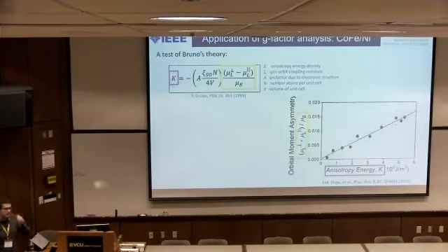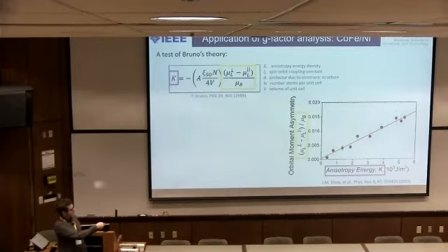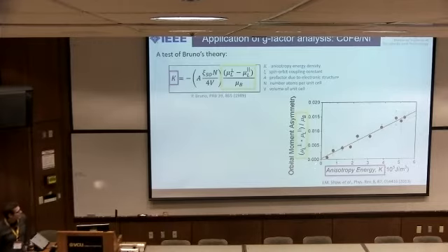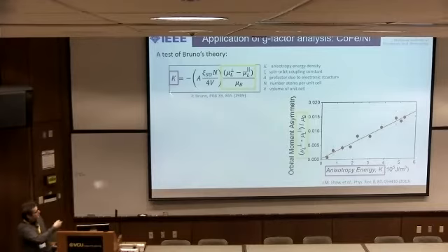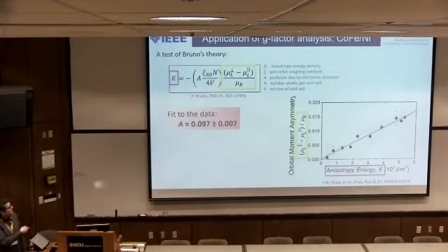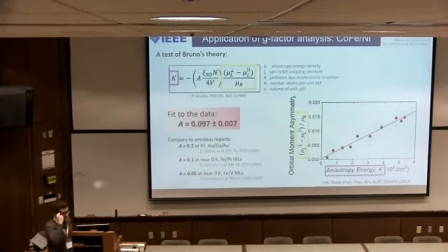So now let's just put it together. From the G-factor data, we're able to extract the orbital moments in the perpendicular direction and in the in-plane direction, plotted against anisotropy energy, and voila, we get this nice linear behavior, which is exactly predicted by this theory from Bruno, showing the proportionality between those two. The only unknown, of course, is this value of A, which comes from band structure calculations, but it's right in line with what is expected and has been measured in similar sort of materials.